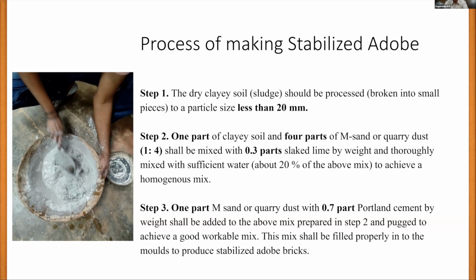So mixing is the most critical part of it. That's where we call it pugging. That is something which has to be done very well using lime, clay soil, and manufactured sand. Once that is done, the third step comes, wherein we mix one part of manufactured sand and 0.7 part of Portland cement by weight. This gets mixed easily, because cement you can mix easily with sand. That is added to the mix in step two and pugged to achieve a workable mix. Once you do that pugging activity, the mix is ready to be filled into the mold.